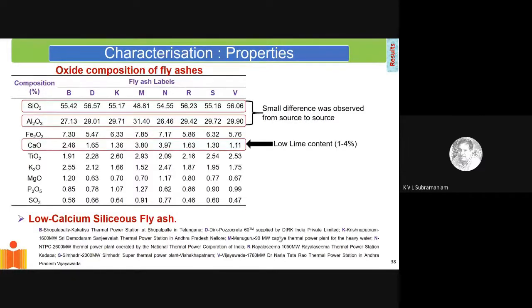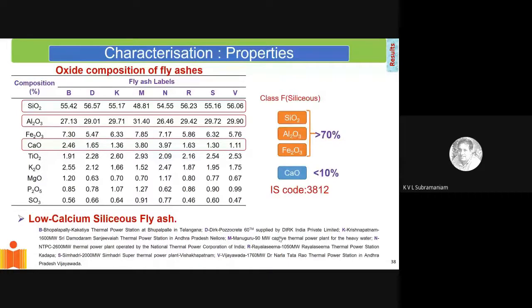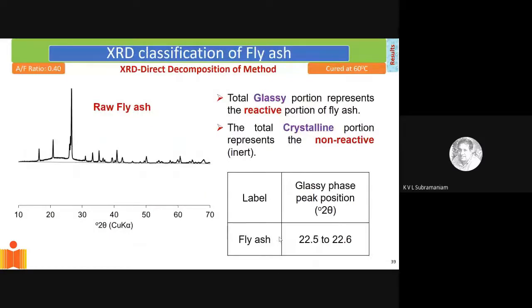And there's very low lime content in our fly ashes. So basically, if you look at the primary oxides in these fly ashes, it's the silicon, the aluminum, and the iron oxide that make up about 70% of the fly ash. But if you remember, we had mentioned that silicon exists in reactive and non-reactive forms. So to identify the reactive and the non-reactive forms, we have to resort to X-ray diffraction spectroscopy.